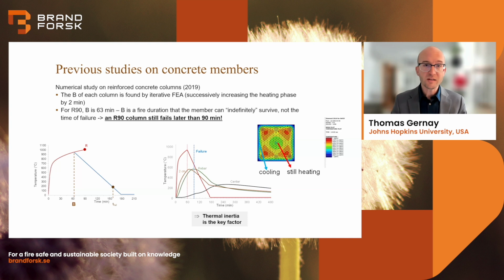So in those analyses, again, we looked at the factors that led to those failures in cooling. And again, the thermal inertia was identified as a key factor by looking at the temperature increase inside the sections over time during the cooling.